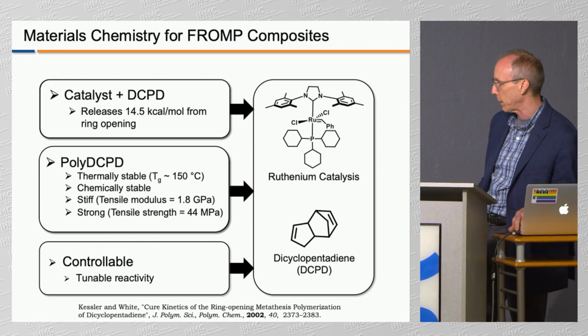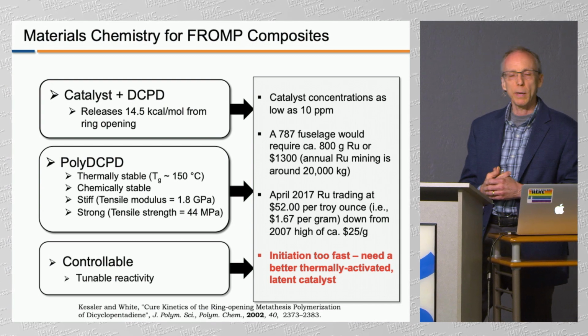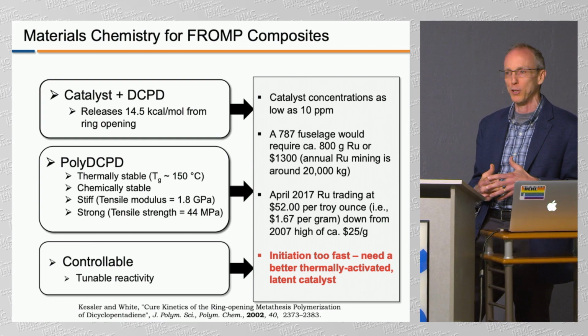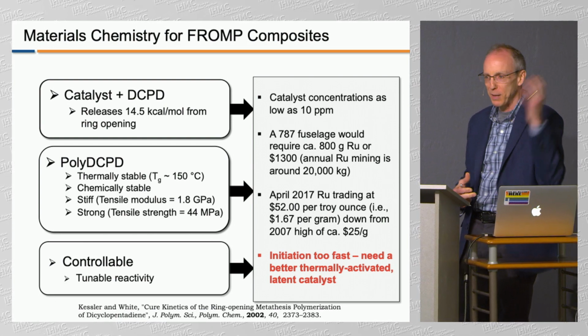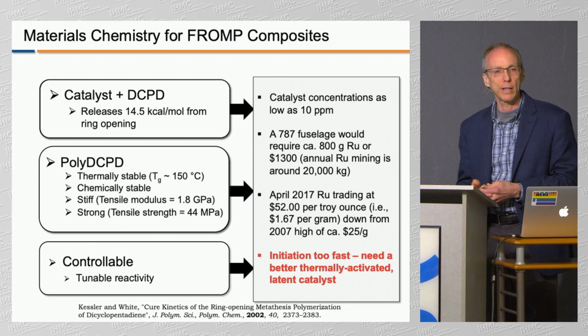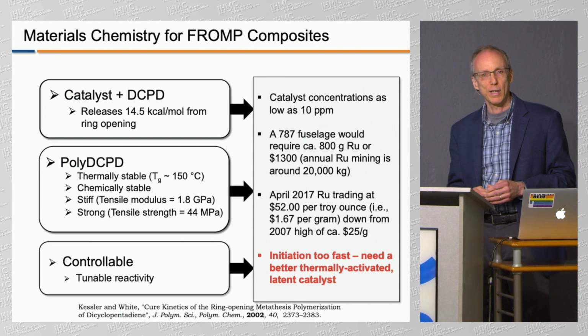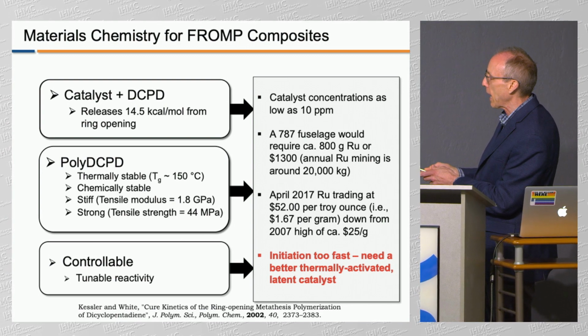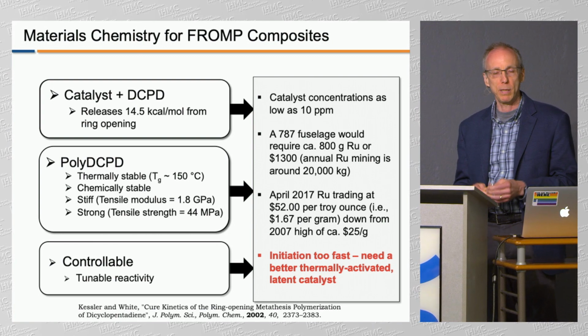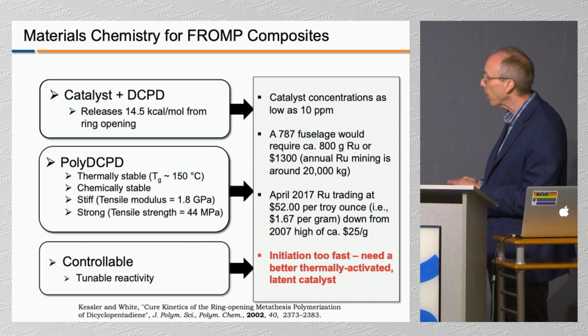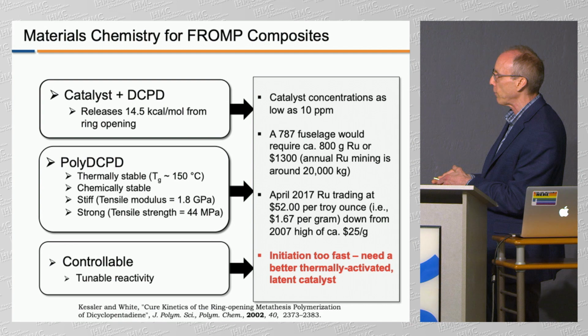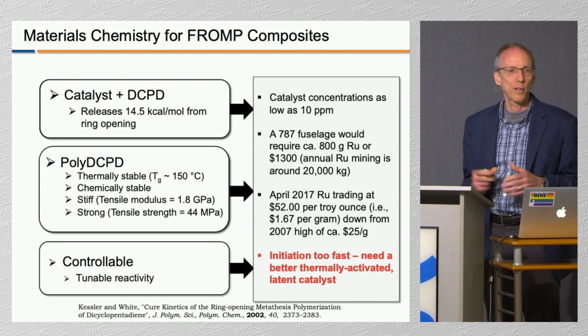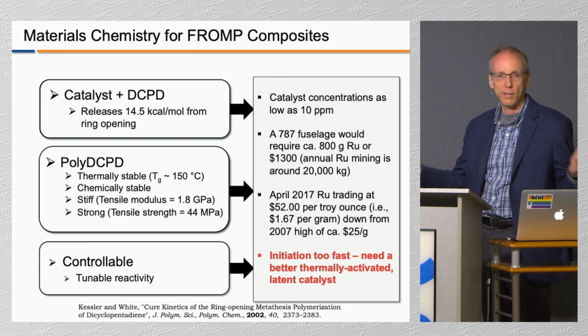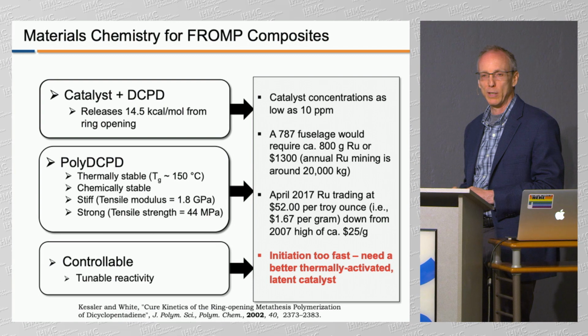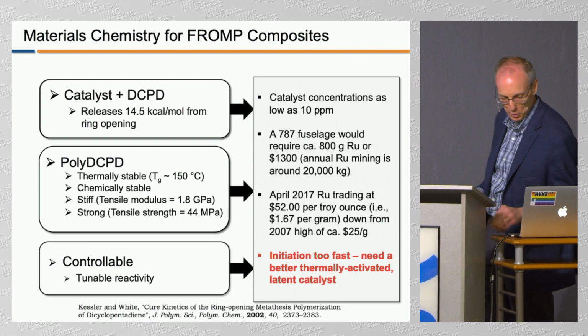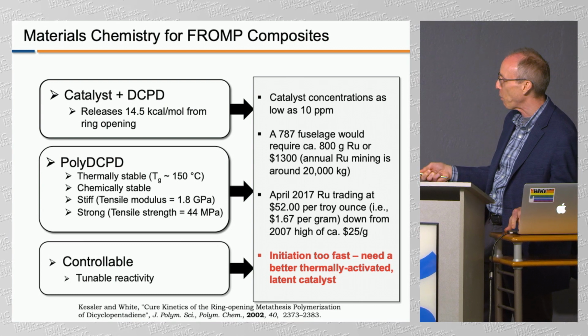I'll show you some movies in a little bit, and then the question is, well, everybody that knows precious metals, if you pay attention to the precious metals commodities, you'll know that ruthenium is up there with all of them. And so then you wonder, could you ever really make a fuselage cheaply enough out of ruthenium? And the fortunate thing is catalysts, when they operate well, you don't need very much. 10 ppm is a really tiny amount, less than 1% of that liquid is catalyst. And so a typical 787 fuselage would have about $1,300 of ruthenium flying around for its lifetime, 30 years. And then at the end of the lifetime, you can decide whether it's worth trying to recover some of that ruthenium or just let it go back into disposal land.